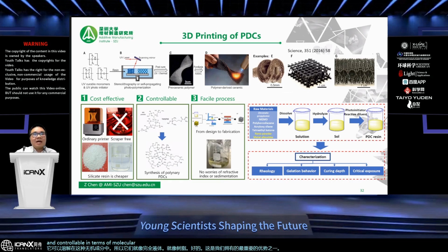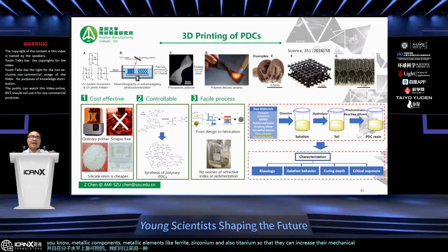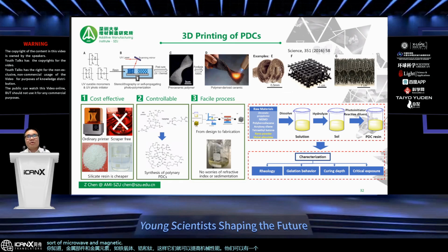And it is controllable at the molecular level. We can dope metallic elements like ferrite, zirconium, and also titanium, so that they can increase mechanical performance. They can have microwave and magnetic properties and so on. So this is very interesting, and the process is very easy. The 3D printing is totally the same as resin 3D printing, liquid phase, with no involvement of powders, and the only additional step is the high temperature pyrolysis.